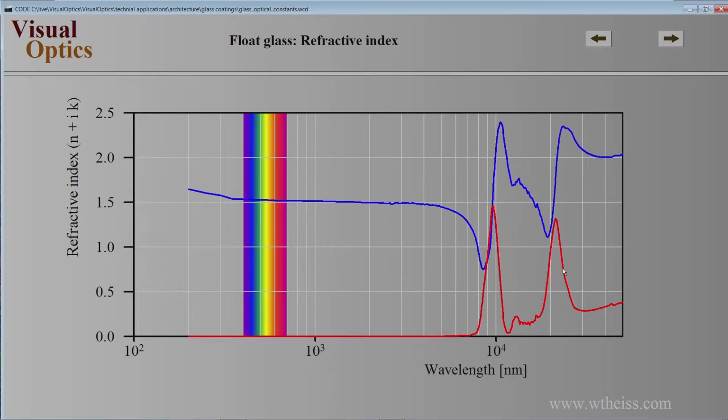Silicon atoms vibrate against oxygen atoms, and you do this by applying the electric fields of the light wave, setting the atoms in motion, and the atoms have some damping, some connection to their environment. So in the end, the whole glass vibrates a little bit, and this means we convert infrared light to heat.